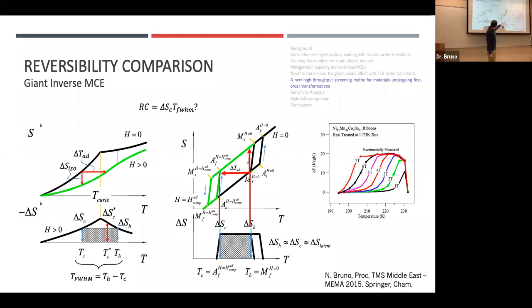I noticed, playing with this stuff for a really long time, that these elbows on my delta S versus T curve actually correspond to my critical transformation temperatures in the shape memory alloy. And actually the width of this curve depends on the adiabatic temperature change, what I'm measuring.